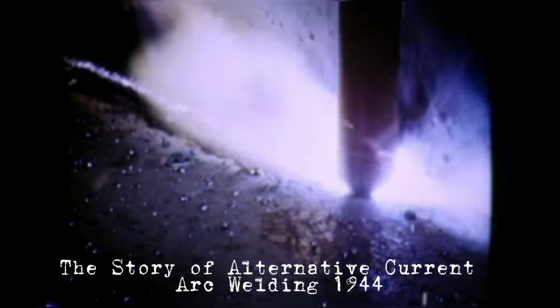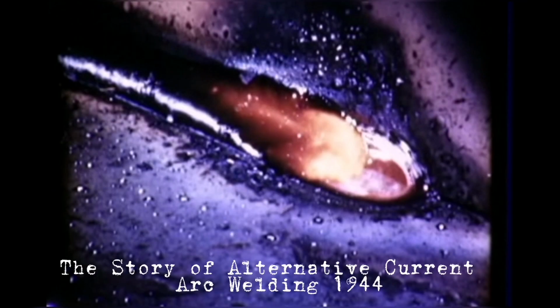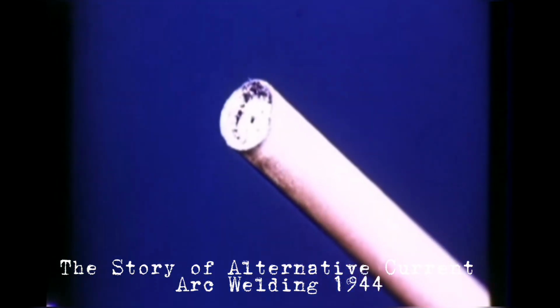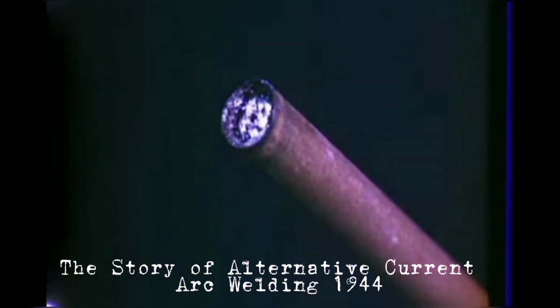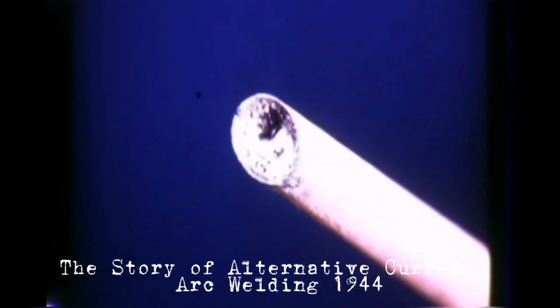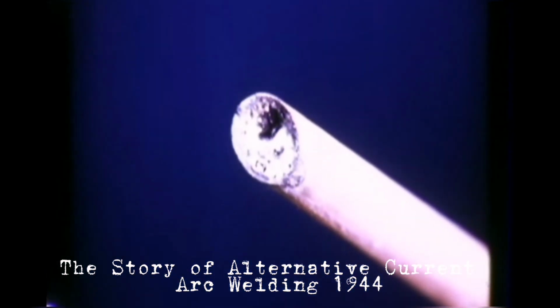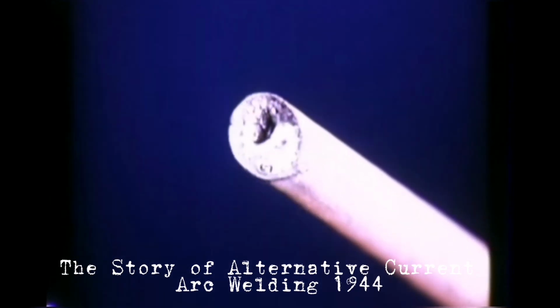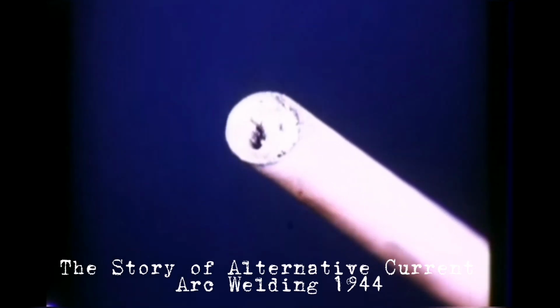The type of electrode used for deep fillets develops a deep, uniform cup when AC is used. The cup automatically maintains the correct arc length when rested on the work. It directs the arc and protects the hot metal from contamination by the atmosphere. With DC, when severe arc blow is present, the cup on the end of the electrode may become distorted due to deflection of the arc. This destroys the usefulness of the cup in maintaining the correct arc length and in directing the arc properly.